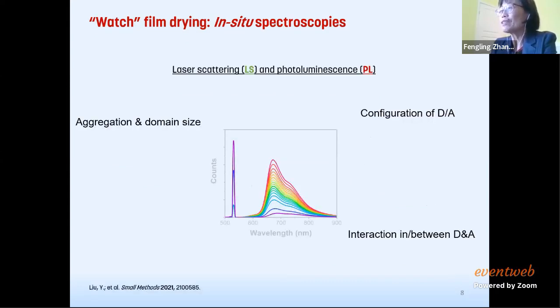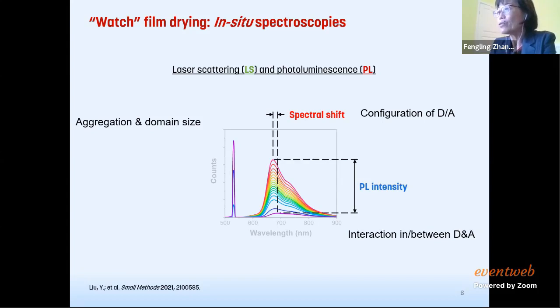So let me explain what kind of information we get from these variations. First, we can monitor whether the spectral peak shifts, blue shift or red shift. That spectral shift gives us information about the configuration of the active materials in the liquid. We can also get the intensity of the photoluminescence, which tells us about the interaction between the donor and acceptor, and of course also the interaction with the solvent. The laser scattering intensity tells us the aggregation size. If the aggregates are bigger, they give stronger scattering. If they are smaller, they give weaker scattering.